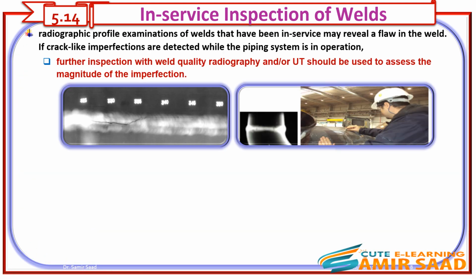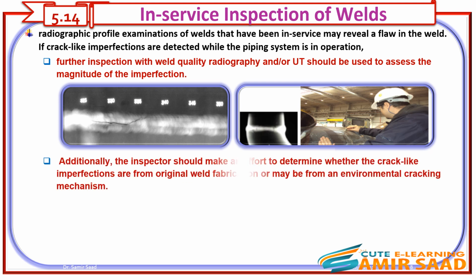Radiographic profile examinations of welds that have been in service may reveal a flaw in the weld. If crack-like imperfections are detected while the piping system is in operation, further inspection with weld quality radiography and/or UT should be used to assess the magnitude of the imperfection. Additionally, the inspector should make an effort to determine whether the crack-like imperfections are from original weld fabrication, or may be from an environmental cracking mechanism.